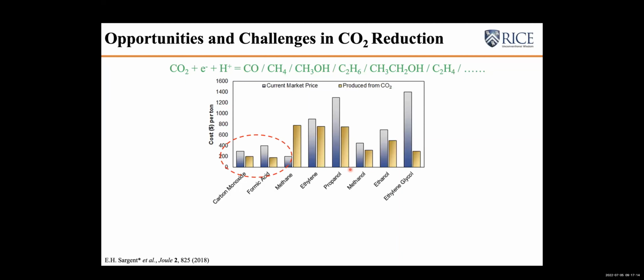There are a lot of things that we need to meet so that we can deliver these attractive targets. First of all, we have to bring up the current density, which is the geometric current per area of the electrode to produce the chemicals. The higher the current density, of course, the smaller the size of your reactor, the device that you will need to have. So the capital cost will be lower. Generally speaking, you have to be more than 100 milliamp per centimeter square to make economic sense. But in commercial water electrolyzers, this requirement could be 1 amp to 3 amp per centimeter square. So this is a very minimal requirement for CO2 reduction.